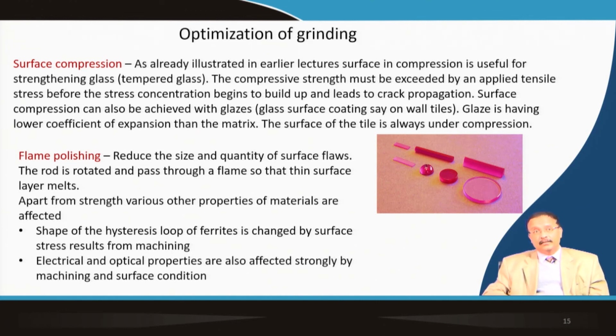In case of laser rods, usually flame polishing is done, and flame polishing reduces the size and quantity of the surface flaws. The rod is basically rotated and passed through a flame, so that the thin surface layer melts. Apart from the strength, various other properties of the material are also affected. For example, the shape of the hysteresis loop of the ferrite is changed by the surface stress resulting from this kind of machining. Certain electrical and optical properties are also affected by machining and surface conditioning techniques.